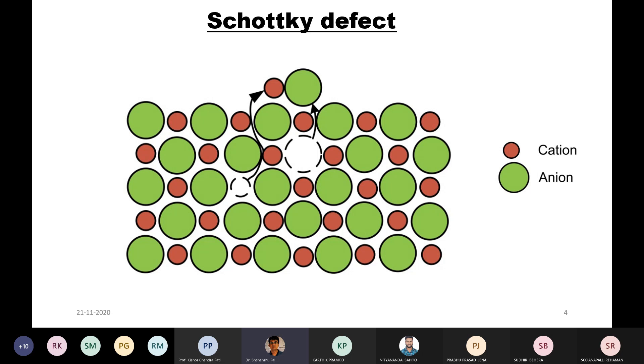In any ionic compound, unlike in a metallic system, defects are present in ionic form. Defect chemistry becomes complex because the need for charge neutrality along with mass conservation is important. Not only must you follow mass conservation, you must also follow charge neutrality, and the fixed ratio of anion and cation sites depending on stoichiometric composition. Along with point defects, electronic defects such as holes and excited electrons are also created in the process.